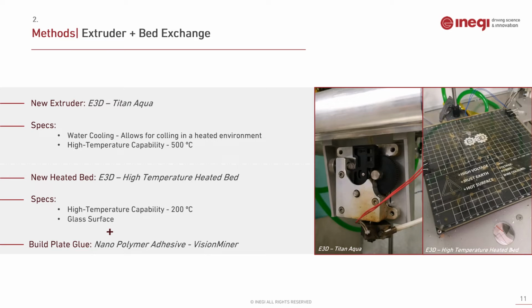For the extruder, we chose the E3D Titan Aqua, as it had water cooling, which was very important for us since this part would be working in a heated environment, which would impair an air cooling system. Other than that, the selected extruder can reach a temperature of 500 Celsius degrees, which goes in accordance with our previously defined requirements.